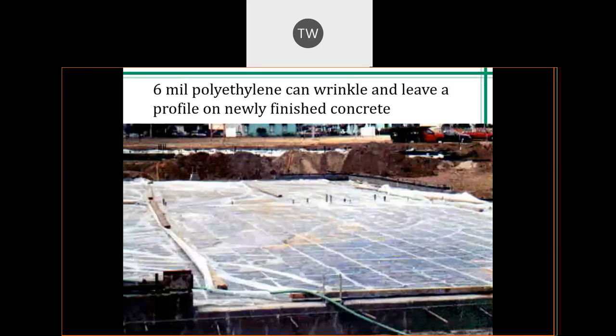So plastic sheets can be applied on thoroughly wet concrete, such as your polyethylene film. This material is a lightweight, effective moisture retarder that is easy to apply. During placement, though, the concrete surface should be hard enough to prevent surface damage. There are some downsides to curing with plastic sheathing, and one of them being the surface profile that is left by the plastic on your surface, which in many cases is undesirable and will lead to extra labor to amend.